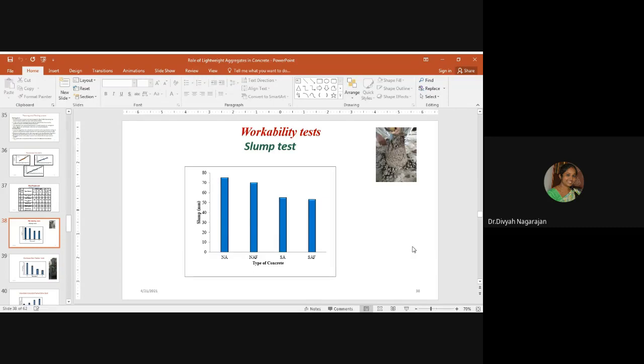The normal weight aggregate concrete had a slump of 75 mm without fiber and 70 mm with fiber. The sintered fly ash aggregates, owing to their round shape and porous structure, produced poor to medium workability results, 55 mm without fiber and 53 mm with fiber. This may be attributed to the packing of the round aggregates. The studies also show that a slump of the lightweight aggregate concrete ranging between 50 to 75 mm is equivalent to a slump of 100 to 125 mm for conventional concrete. Medium workability is also obtained by adjusting the dosage of superplasticizer.